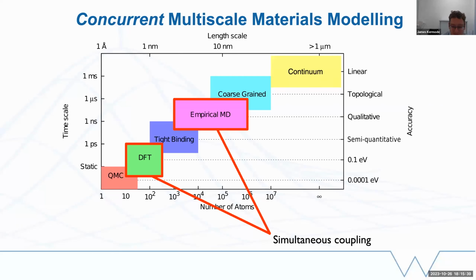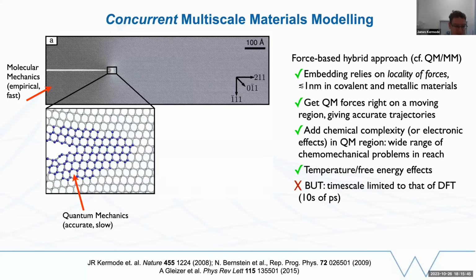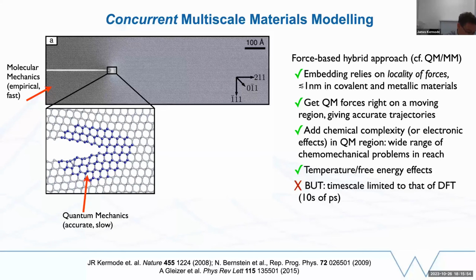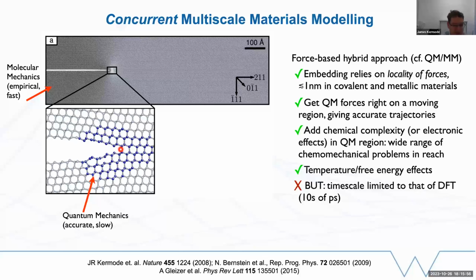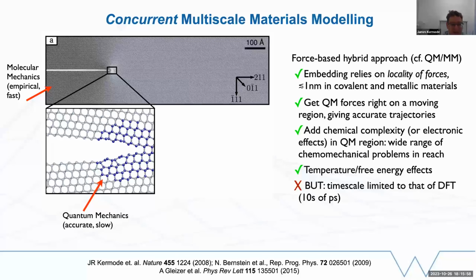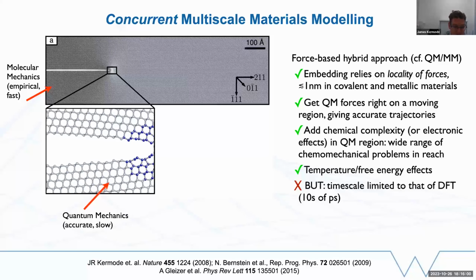But we still retain sufficient accuracy when and where we need it. So if we return to the brittle fracture example that I showed earlier on, this is the same system, silicon cleaving on the 111 cleavage plane. If we look at what happens when we treat a couple of hundred atoms near to the crack tip with density functional theory, we now recover the mirror smooth fracture surface that's seen in experiment.